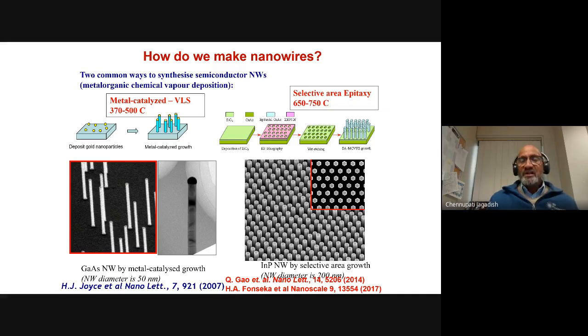You can see this nice, beautiful structure here. These ordered patterns of indium phosphide nanowires, beautiful hexagonal facets, and these nanowires are growing in the 111 orientation because that's the lowest surface energy orientation. We typically use 111 substrates in order to be able to do that. This is the work of Dr. Qian Gao. Now she's at BluGlass in Sydney, working as a research engineer, trying to make LEDs and glass, for example. Again, in this case, we have made nanowires as small as 70 nanometers, as big as 700 nanometers.